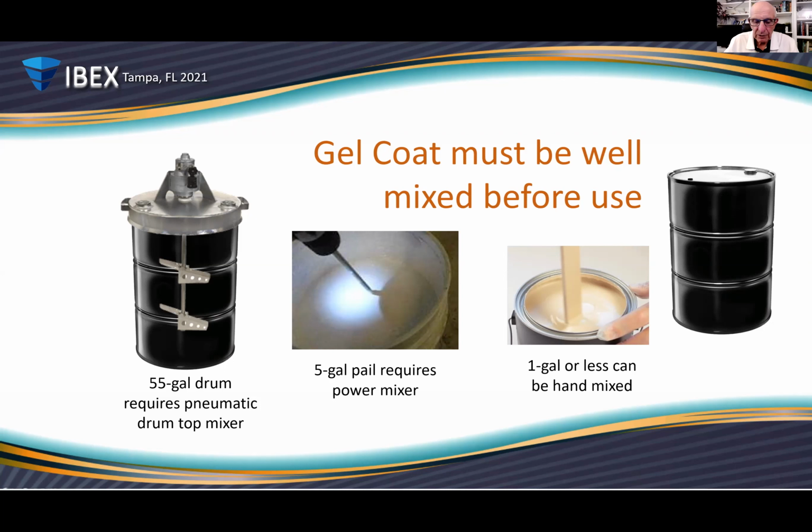And when we started going through all of the data and correlating the data, you could actually track the defects from the first use of the container, when all the heavy material was on the bottom, down to the bottom, or draining the last stuff off the top with the light viscosity. So the bottom line is you really need one of these blade type drum mixers.